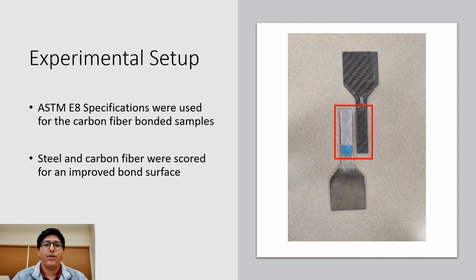I created the first single lap bonds with West Systems 105-206 resin and hardener, which is an impregnating epoxy. This was chosen because it's what the team believes was used in previous research done on carbon composite suspension links. There were two samples made, one cured at room temperature and another cured at 170 degrees to decrease the viscosity of the epoxy and reduce the number of air bubbles in the bond.